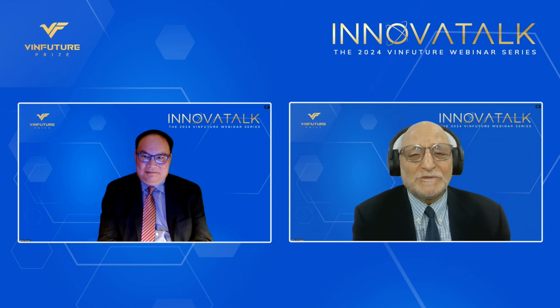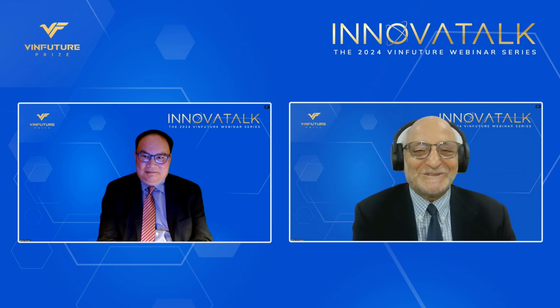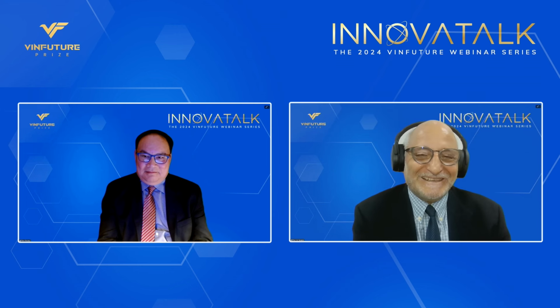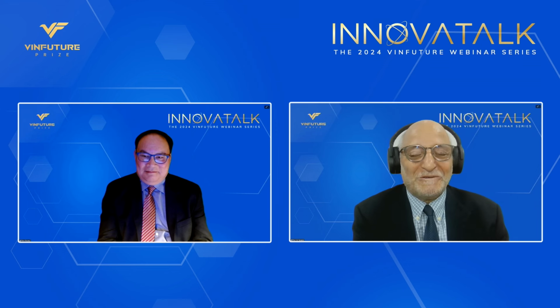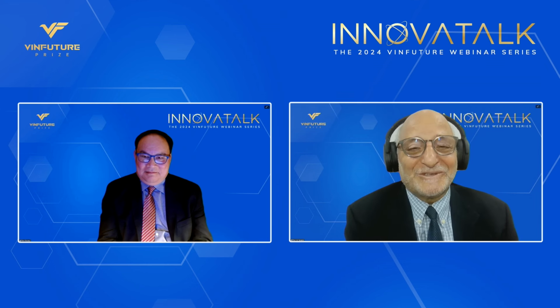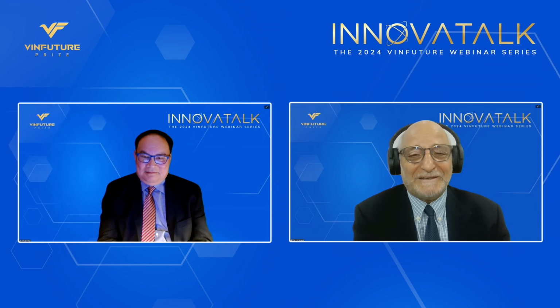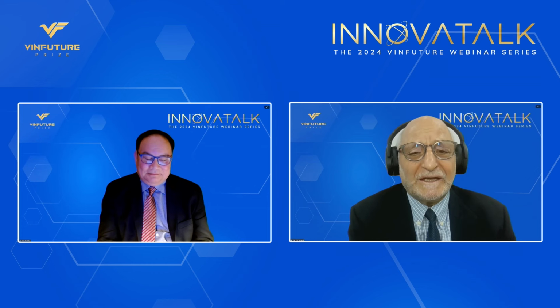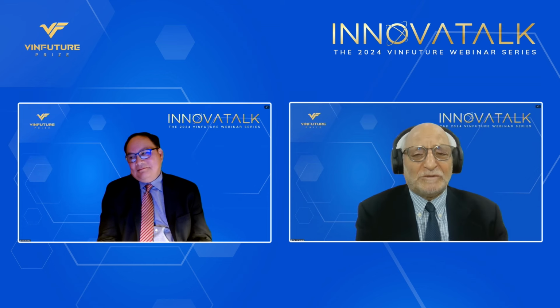Now we go below 30 minutes, which is recommended by Mr. Duong and the Department of Energy, and I fully agree that we have to go below 30 minutes, if not below 20 or 15 or even 10 minutes. Of course, as we shorten the charging time, we put the battery under stress. So there are different ways to cope with this.